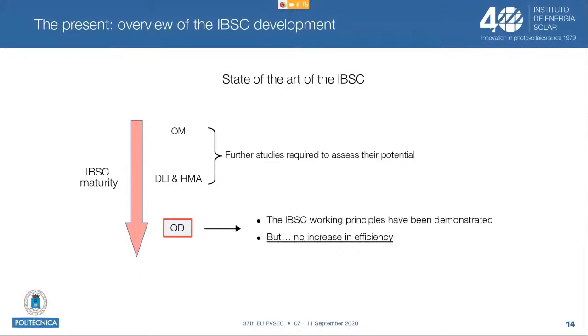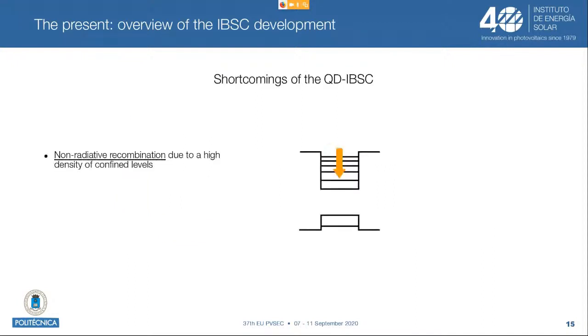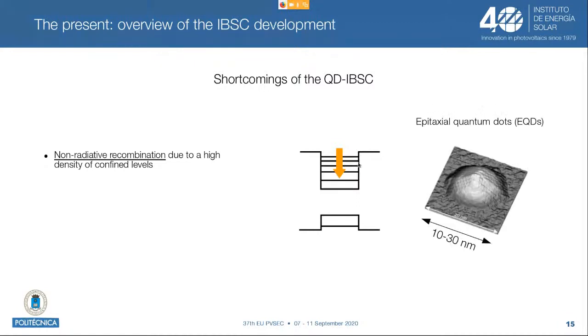So we will see why. I will briefly comment on the shortcomings of the quantum dot IBSC. The first one is that there is extra non-radiative recombination in the quantum dot, and this is due to a high density of confined levels, as you can see in the graph. And this high density of levels is due to a somewhat large lateral size of the quantum dots, which in turn is inherent to the fabrication method of the dots, because in the IB community, when we are talking about quantum dots, we usually refer to epitaxial quantum dots, and they tend to grow in this lentil shape.